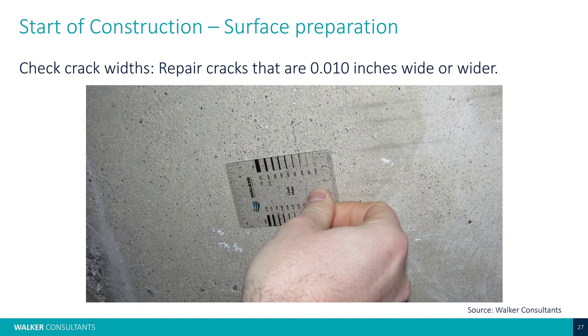A lot of times that's an injection process. However, if you're in a high moisture environment, let's say some parking garages, where you might expect moisture to come through cracks, you might even want to fill cracks that are even smaller than that. So again, verify with your engineer, verify with the manufacturer that we're okay with the 0.01 crack width for repair.